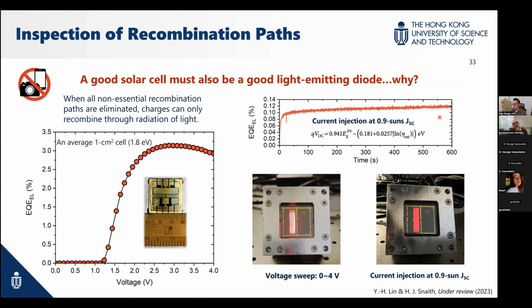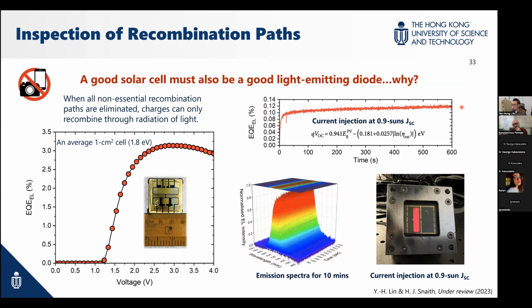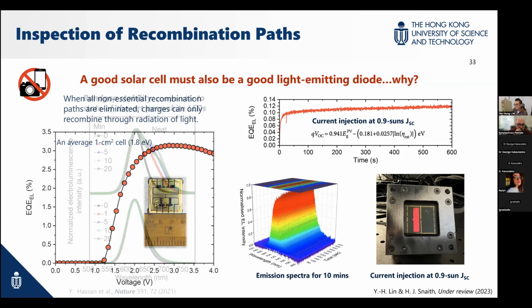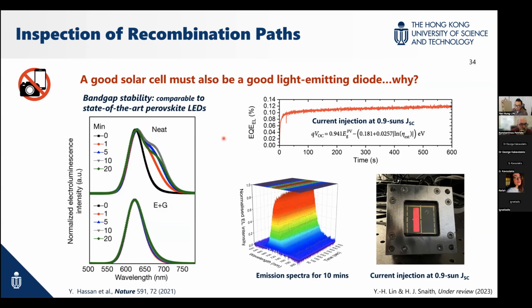So you can see this is the emission photo. Over a time period of 600 seconds, it remains very good EQE. But the most important thing is that the spectrum stays right at 700 nanometer during these 600 seconds. Why is this important? Because in order to get this emission, we need at least 40% bromide in the composition. So what will happen when we have this kind of mixed cation, mixed anion system?